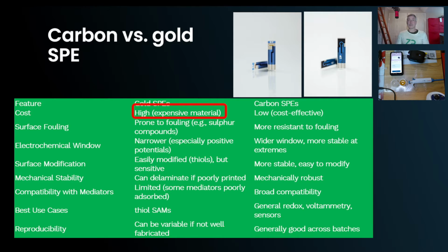This is a luxury material that's used to hold wealth. It's traded essentially as a wealth asset, and then we're competing for that material when we try to combine it into electrodes. So I would really say that building assays and thinking that you're making a low cost assay when you've got gold intrinsically tied up in that assay is not going to lead to low cost. Whereas if you look at carbon, mass for mass it is 1/28,000th of the cost. It's a hard term to say, but 1/28,000th of the cost of gold.